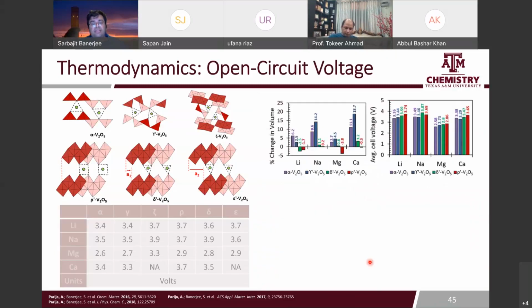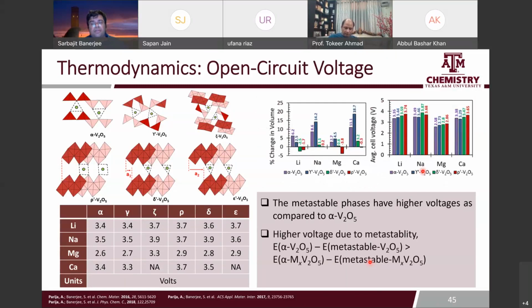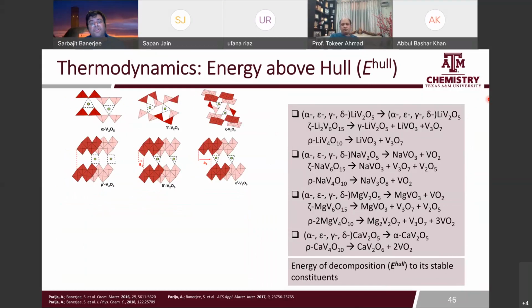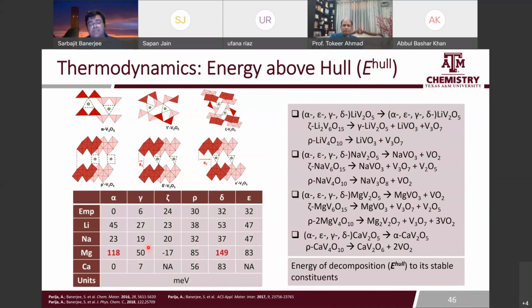And this is an example of some of these numbers that we get, just sort of plotted out. And you can see also why people like calcium. You can easily access about 3.5 volts here. Okay, so well, metastable phases are all good, but can you actually access these phases? And the answer is yes. If you can be within reasonable range of the convex hull of the most stable constituents, we'll be able to access these phases, and we can actually see that here with a few exceptions. Like I said, magnesium and alpha is very difficult to access, but the rest of these phases tend to be quite reasonably accessible, even though they are metastable.